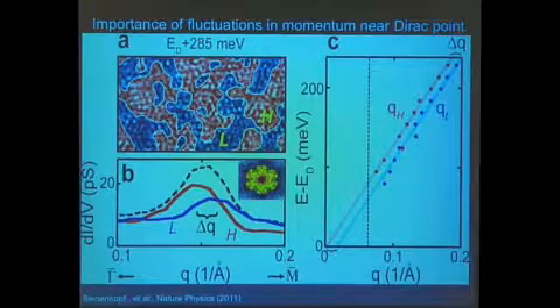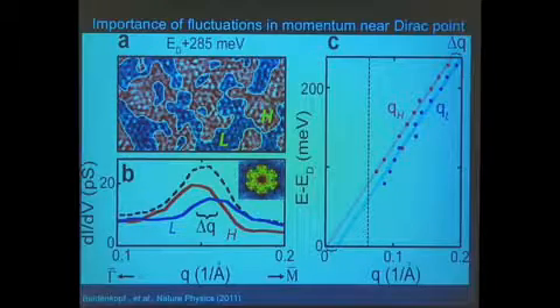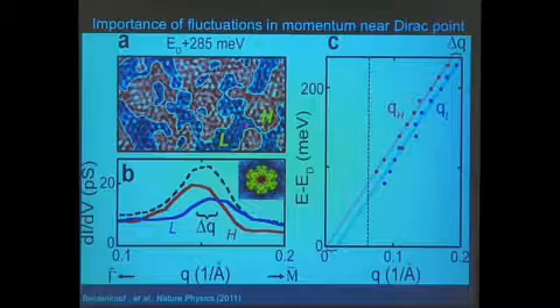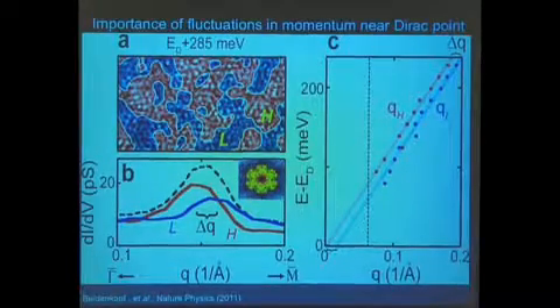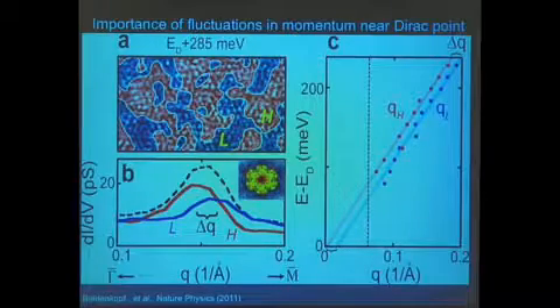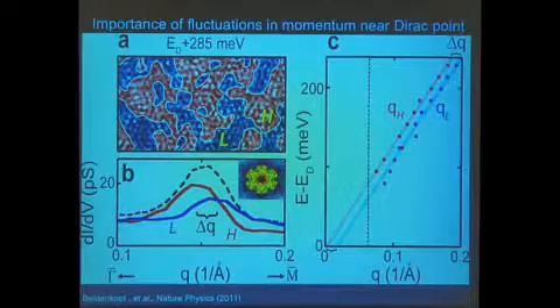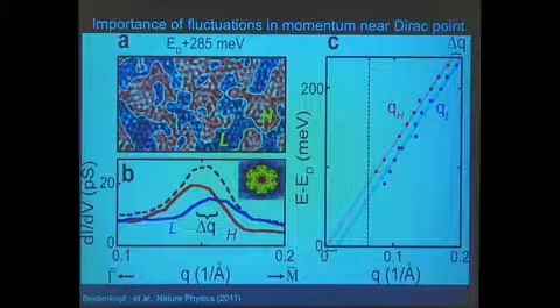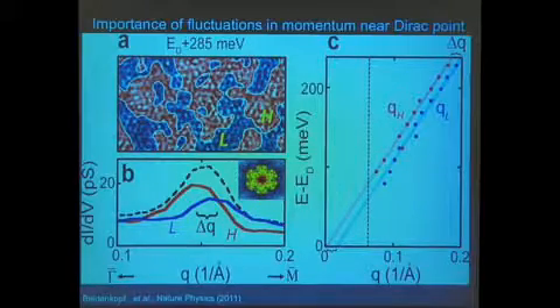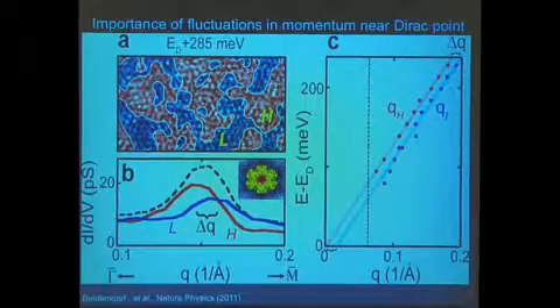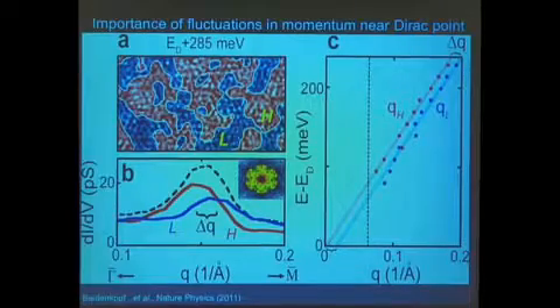Now, what's interesting here is that this disorder potential is very important for these electrons as you get very close to the Dirac point because the wavelength gets very long. And this is showing you that the scattering wave vectors become ill-defined as you get very close to the Dirac point in this compound. This is because of the disorder potential in the sample, and it has major consequences for the transport through this electronic state. Yes?